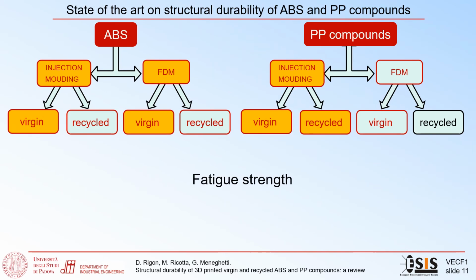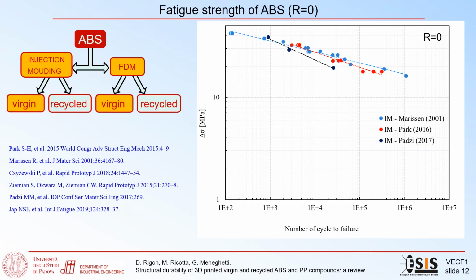Now let's move on to the fatigue test results. Here we have the same flow charts which identify the data available from the literature. About the ABS, only virgin material can be found in the literature, so we can compare just the technology used. For the polypropylene compounds, we can compare only the virgin and the recycled injection molded materials. Starting with the virgin injection molded ABS, here we have the fatigue test results taken from several papers found in the literature, expressed in terms of stress range against the number of cycles.